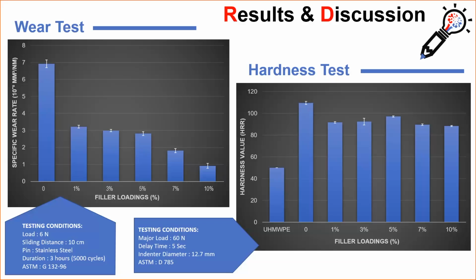The incorporation of 1 weight percent of ultra-high molecular weight PE has reduced about 53% of the wear rate of the composite. As the amount of PE filler increased from 1 weight percent to 3 weight percent and 5 weight percent, the specific wear rate shows a small gradual reduction trend, with 7% and 6% respectively. For 7% and 10% filler loading, the reductions in the value of specific wear rate are quite obvious. When the filler loading increased from 5 to 7, there is a 36% reduction in wear rate. As the filler loading was further increased from 7 to 10%, a 50% reduction in wear rate was observed.